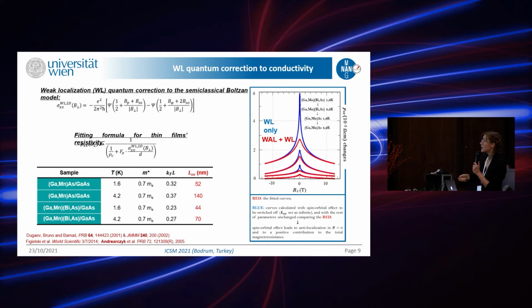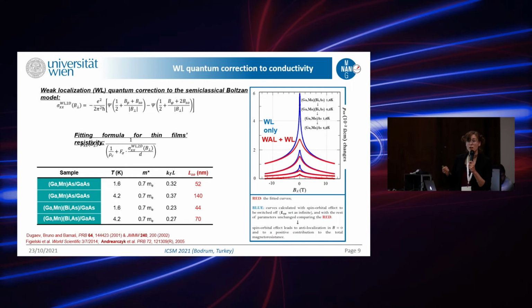We have a twice reduction of L_SO in the case of gallium manganese bismuth arsenide compared to gallium manganese arsenide. Less propagation distance, or less distance where spin-orbit interaction plays a role, means there is stronger interaction. Means we have a 200% increase of spin-orbit coupling.